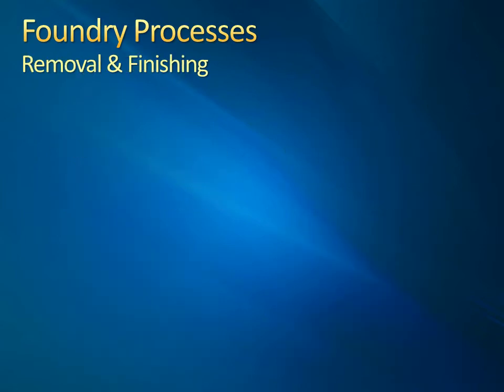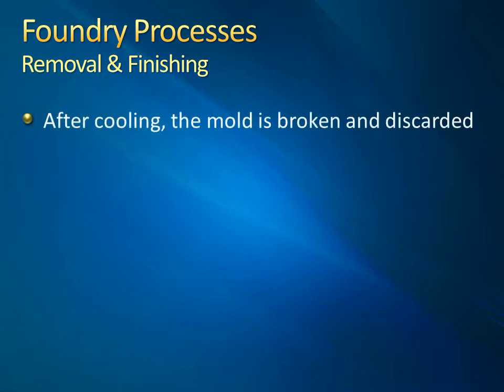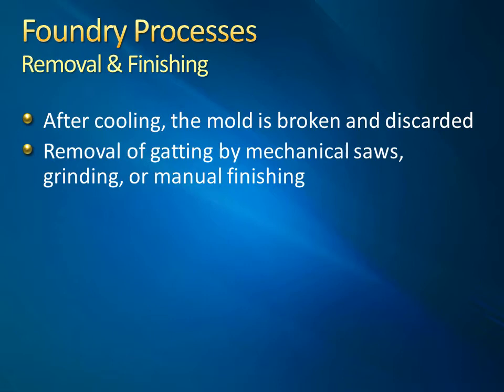After the casting is cooled, the sand mold is broken off of the casting and discarded. The finishing process begins by the removal of the gating by mechanical saws or grinding. The casting is then cleaned using grit or tumbling devices to smooth out any burrs or imperfections in the casting.